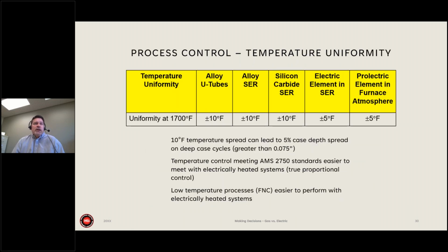As far as process control, we mentioned temperature uniformity, and the gas heating options here are probably limited to plus or minus 10 degrees Fahrenheit, depending on the furnace application, specifically for this batch integral quench furnace. And then you can get down to plus or minus 5 degrees using electric heating options. A 10-degree temperature spread can impact the process to have a variation of 5% case depth in a carburizing cycle for deep case cycles. So the temperature is important. So going to electric, if you have deep case cycles, could be one of the options or decision points.